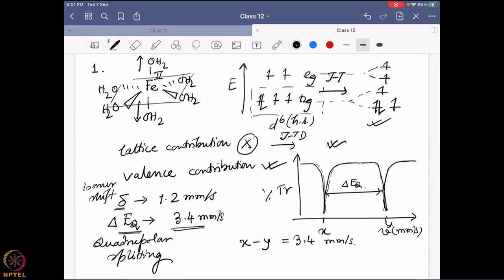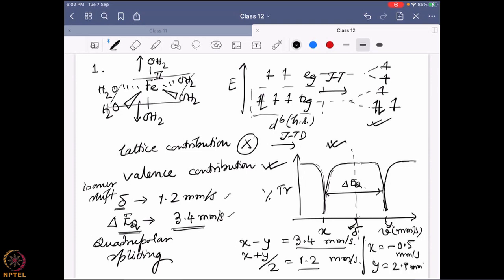And what is the average of x and y? That means what will be the peak before it split? That is going to be the value of the original isomer shift. So x plus y divided by 2, that will be 1.2 millimeter per second. That will be the original delta value, which is 1.2 millimeter per second. And delta EQ is 3.4 millimeter per second. So now if you solve this equation, you can find x and y. So I'm not doing the full math. X is minus 0.5 millimeter per second. Y is 2.9 millimeter per second. So you can say this is minus 0.5. This is 2.9. So these are the values we are getting, and that is how you actually find out where the lines would be.